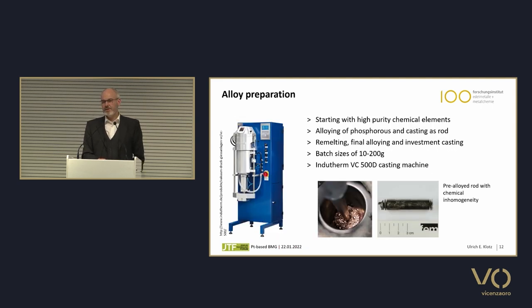So therefore, we started melting in a conventional induction heated casting machine. We used high purity chemical elements. We apply them in a special way to avoid the sublimation of the phosphorus and to allow the alloying of this. And we tried this first with small batches of a few grams, and then later on increased it up to 200 grams. We end up with a small pre-alloyed ingot. This ingot is still chemically inhomogeneous, so we cut the discs on either side and measure the phosphorus content, and it was not homogeneous. And because the phosphorus content is so decisive, we need to remelt the material in a second try. But it's quite convenient to alloy the material this way in a closed machine.